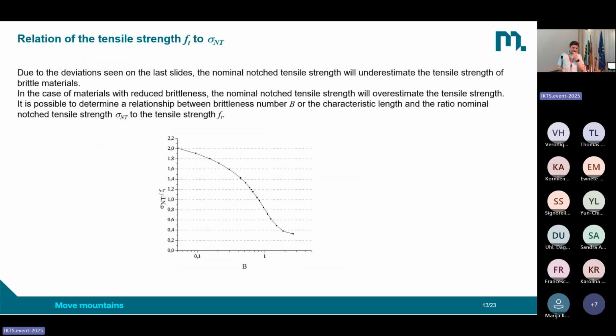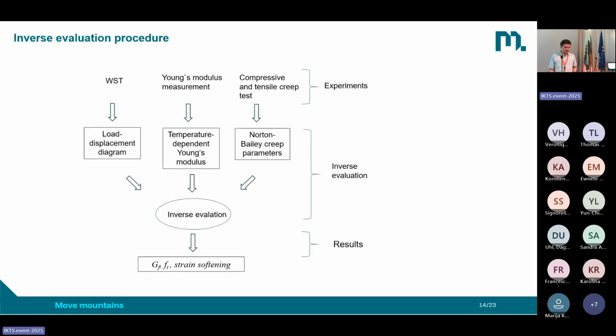And how is it not accurate? We can see here in this diagram, where I plot the result for this relation, nominal notch tensile strength to tensile strength, over the brittleness. And you see for very low brittleness that the nominal notch tensile strength overestimates the tensile strength. And for very brittle materials, it underestimates the tensile strength. So now we know, okay, nominal notch tensile strength is a parameter which does not represent the tensile strength. We know we have these deviations. How can we deal with this problem?